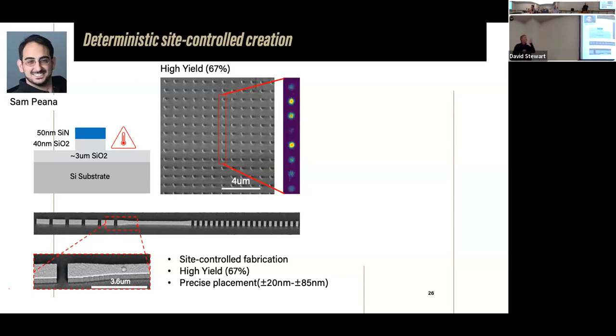So far, we didn't do anything. We just did it, and we immediately obtained this pretty high yield. To compare with other single photon emitters, which typically have a random Poissonian distribution, you usually get only a few percent, and here we got this 67.